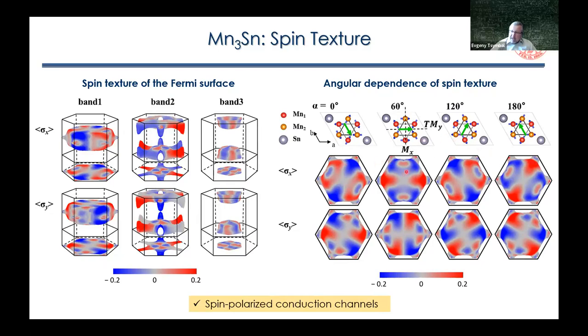However, if there is some angle between the magnetic moments, then what I've shown here is opposite. So when we flip the magnetic moments from 0 to 180 degrees, we have a complete mismatch between the spin orientation in the left and right electrodes, from blue to red for the X component and also for the Y component. Everything changes to the opposite. However, if you have parallel orientation, we have a perfect matching.